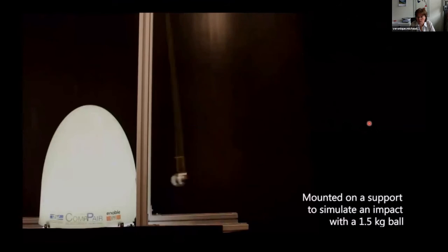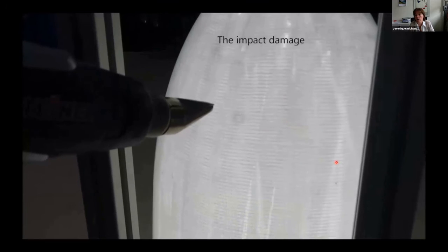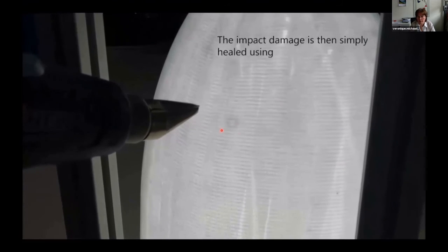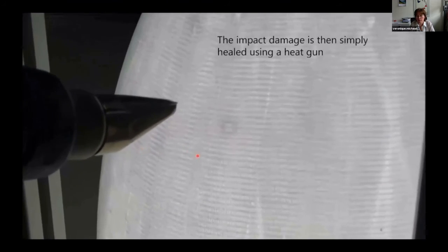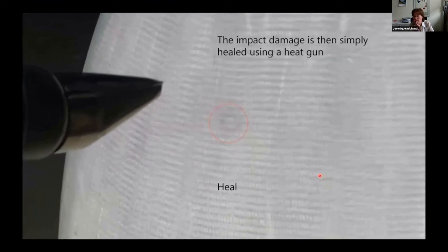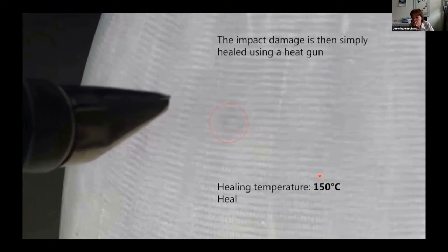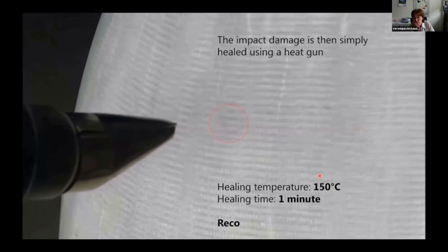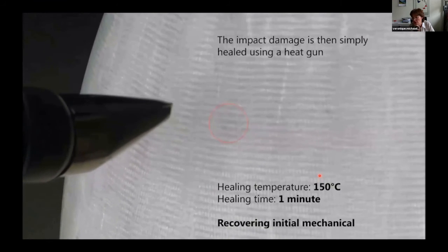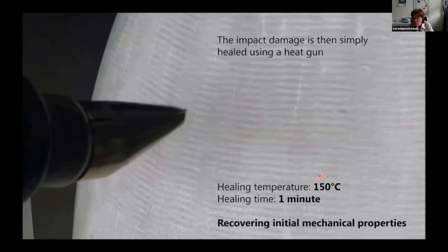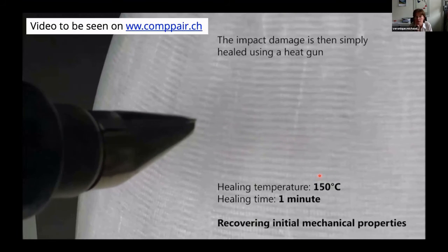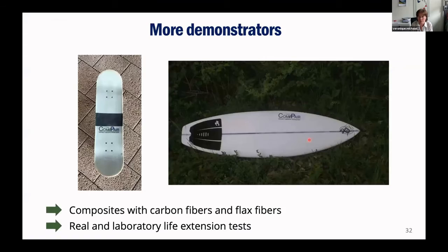So we have a big ball here, 1.5 kilograms, that is impacted from quite high. Then we see the impact damage is here. We heal it for 1 minute with a heat gun, and the impact disappears at about 150 degrees. And we recover the initial mechanical properties by compression after impact. And so this part we've used a lot, and it's been impacted many, many times, and it still looks quite okay, I must say. So we're very happy about this.